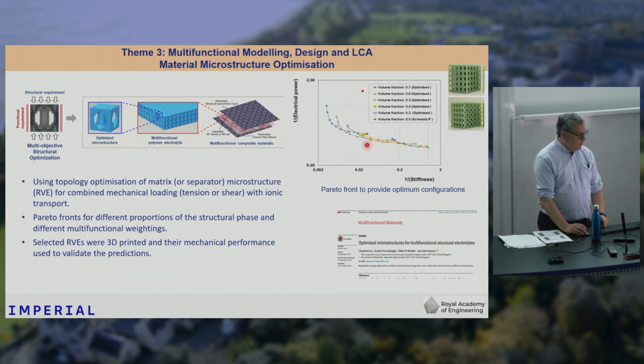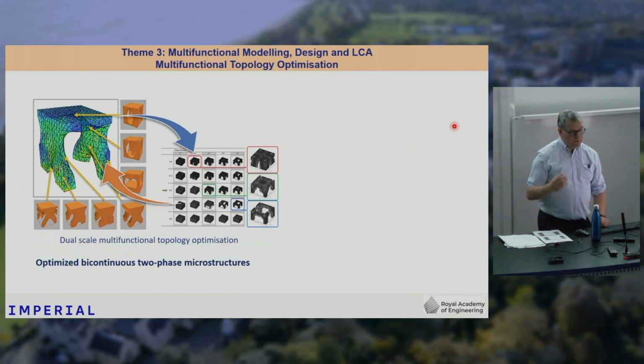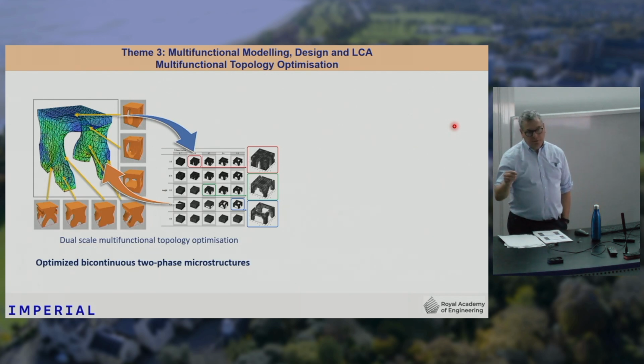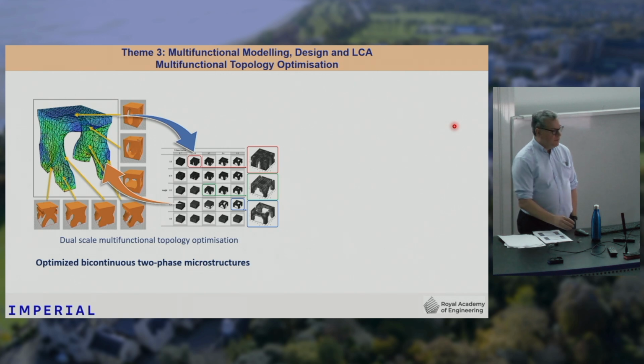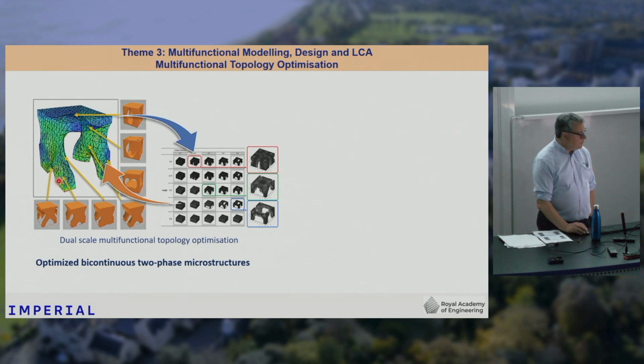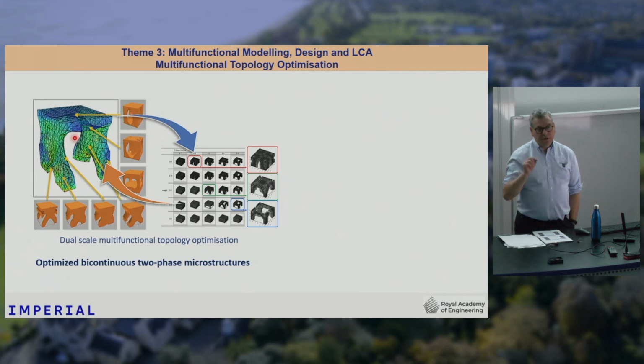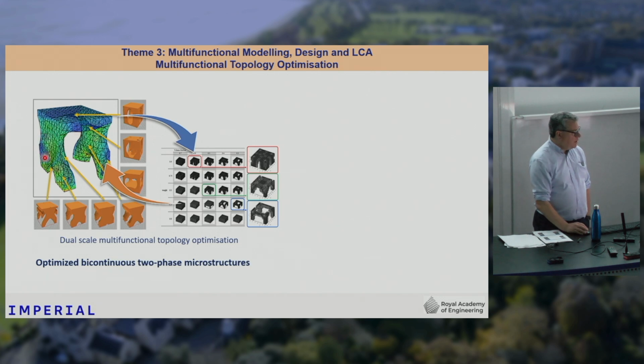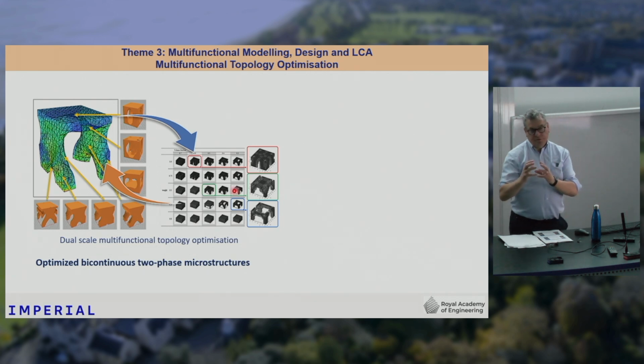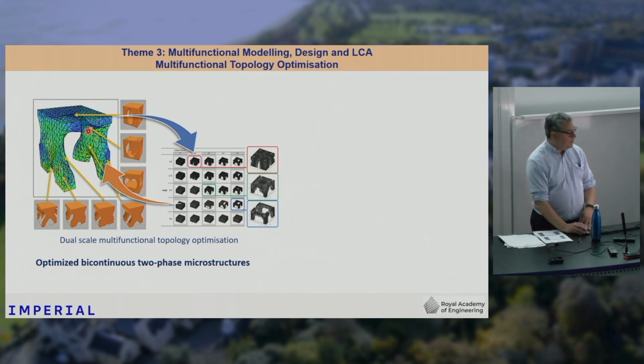So this was an exciting piece of work that we're really taking forward now, and we've started to look at the concept of multi-scale topology optimization. If you consider one of those unit cells shown here, this is one that's optimized for shear loading. If you scrutinize that microstructure, there are some regions that are seeing high direct loads and some regions that are seeing high shear loading. So what we're able to do is have a library of different motifs and then implant those into this larger scale motif to give us an optimized